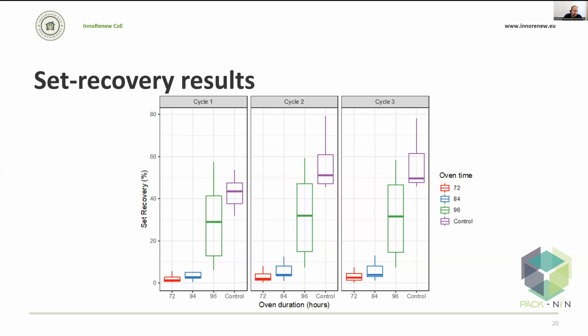So you want some level of moisture still in the wood. Not only is it over dried, but it can also pre-cure the resin, which causes problems. Phenol resins cure at higher temperatures, and they just cure faster at higher temperatures, so there can still be some reaction going on at lower temperatures. We think it's a combination of these things. This is good to know because drying takes a lot of time and money. So it's good that the better results are with shorter drying times.